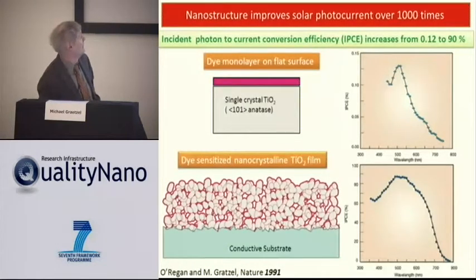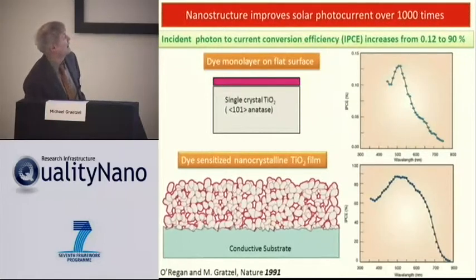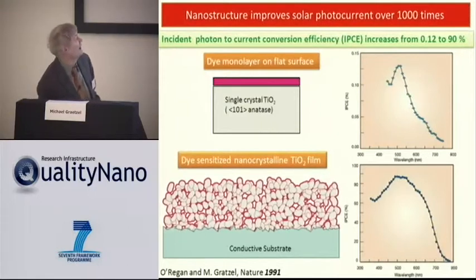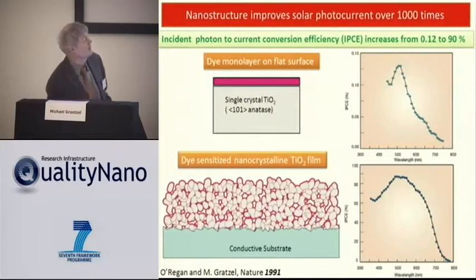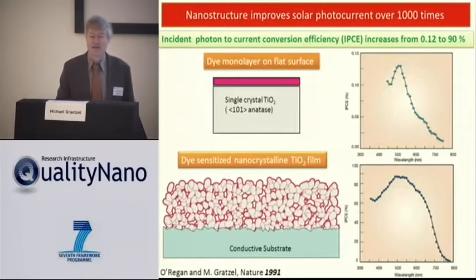If we take a single crystal and we put the dye on, yes, you see a current flowing, and this is the incident photon to current conversion efficiency. But you see the efficiency for each photon that hits the cell, at best we get 0.1% electrons back. That's very little. But if we go to the nanocrystal film, well, we get over 80% back. And so that's actually the core of the discovery.